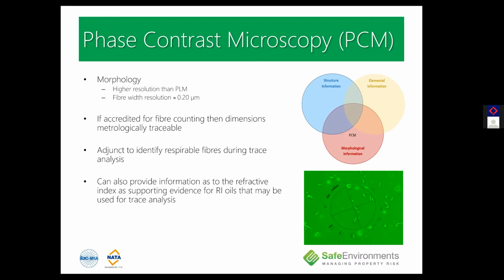PCM has the ability to identify respirable fibres with widths of 0.2 microns at a magnification of about 400 times. This resolution is important as it is the basis of the minimum detectable fibre widths used in epidemiological studies. If lower fibre widths are examined and counted, this unravels the association of exposure with the probability of the end health effect. Consequently, if electron microscopy is used, which detects finer fibres, then the associated risk is not valid. And this is the purpose of using the HSE test slide under phase contrast microscopy, as it's a biological check on the analyst.